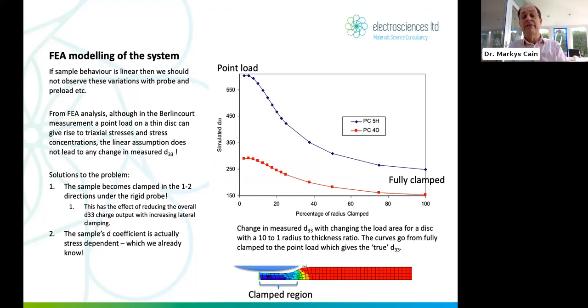And we can see this here, a little FEA modeling that we did. When we say, okay, so we have a piece of ceramic down here. Okay, this is just half of it. And we have a dome-shaped contact here, and we're applying a pressure. I'm looking at the FEA plot down at the bottom, by the way. And we're applying a pressure with this contact here. And we're saying, what's the difference in the simulated d33 as a function of basically the size of this probe, compared to the size of the whole material. So the radius, the percentage of the radius that's clamped.